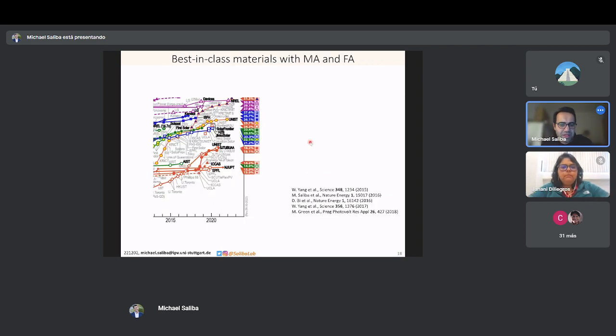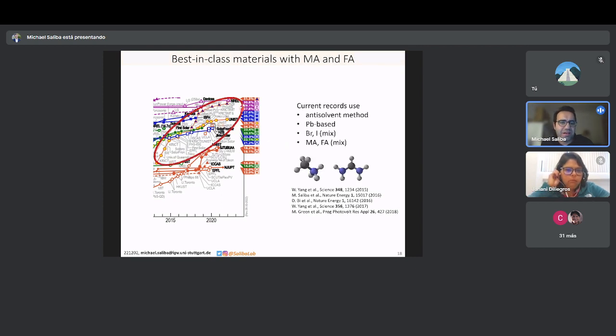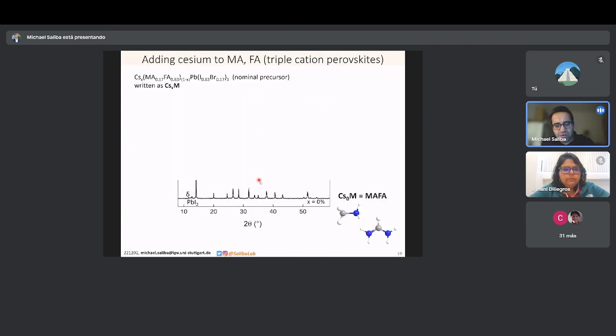So first of all, in 2015 already, or 16, when this work started, it was already very clear that practically all the perovskites there are, so this is from the NREL chart just taken this morning, are lead-based, using mixtures of bromine and iodine, anti-solvents as well, and mixtures of methylammonium, formamidinium. So it was interesting that these double cation perovskites were leading in the community. They're still leading in many other ways as well. And when you look at these extremely high-performing perovskites with MA and FA in the cation position, it's still very apparent that they have this delta or yellow phase as an impurity.